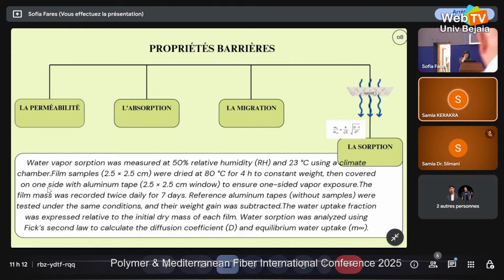And the last one is sorption, where water vapor sorption was measured at 50% relative humidity and 23 degrees Celsius using a climate chamber. The test is explained in this slide. Then let's go to see the experimental part of this study. The next slide, please.